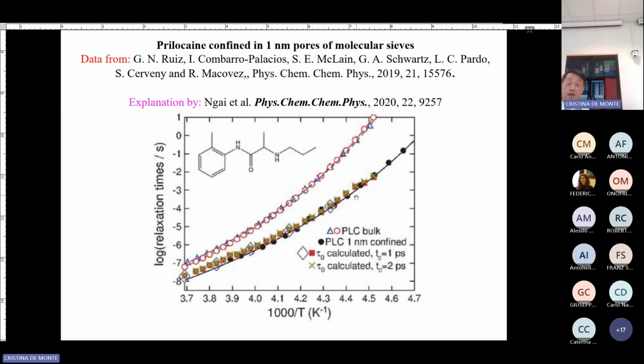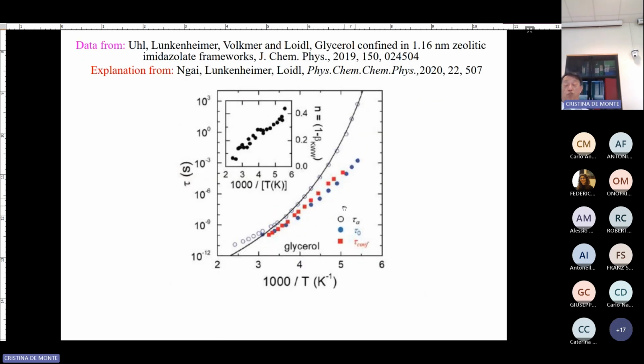So this is one, and you say, well, is it general? Yeah, well, it is. And this is done by the group of Lunkenheimer and Loidl, and they did it again with our old friend glycerol. Everybody loves glycerol, even though it's such a workhorse. And they do it again the same way by confining it in 1.16 nanometer zeolitic imidazolate framework. This is a very high-tech material. You can put it in there. 1.1 nanometer, very confined. So even for glycerol, you know the n value.